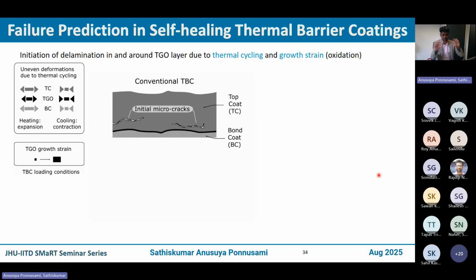So imagine the bottommost layer is the turbine blade in your aircraft engine. These blades, made of nickel alloys, are exposed to 2000 degrees, and that's why you coat these nickel alloy blades using ceramic layers, made of yttria stabilized zirconia. But forgetting about the details, what happens in such coated blades is that micro cracks form for multiple reasons. One is that an aircraft takes off and lands, which means micro cracks develop because of thermal expansion and contraction. And here we are talking about combinations of metals and ceramics. Naturally, they expand and contract differently, so micro cracks grow.